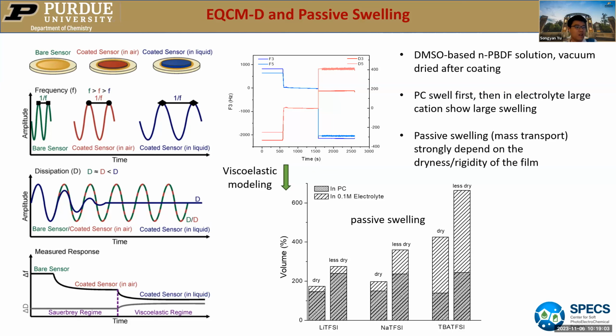Another thing I want to mention is that even for the same electrolyte, with a dry film and a less dry film, the swelling in PC and in the electrolyte is different. So it's strongly dependent on the dryness and rigidity of the film. Why do I want to mention this? Because it also influences the mass transport in the electrochemistry.